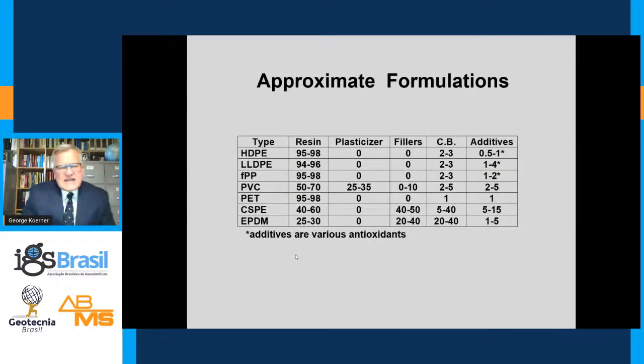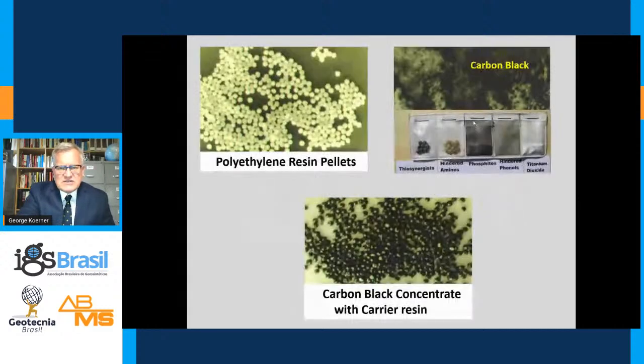Please realize I say HDPE, but this is a formulation. There's a recipe associated with this. The vast majority of the HDPE or polyethylene is resin, 95 to 98%. This material does have carbon black and additives associated with it. These additives and carbon black are only in there a few percent, but they're the expensive part of the formulation and certainly needed to make these materials last a long time, even in harsh conditions.